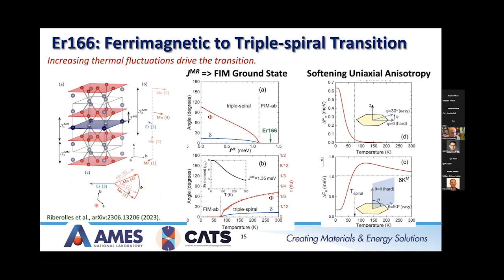So in this bottom graph, the numbers correspond to the layers on the top going up. So you have manganese 1, manganese 2, erbium 3, manganese 4, manganese 5. Within a manganese bilayer, you get this small splitting delta. And then between the manganese bilayers, you get this overall turn angle of phi. It's this angle phi that corresponds to the antiferromagnetic propagation vector. And then the erbium ions bisect this angle phi minus delta, but point against the bisector, so they point in the opposite direction. This is similar to a structure that was seen for gallium doped thulium manganese 6 tin 6.